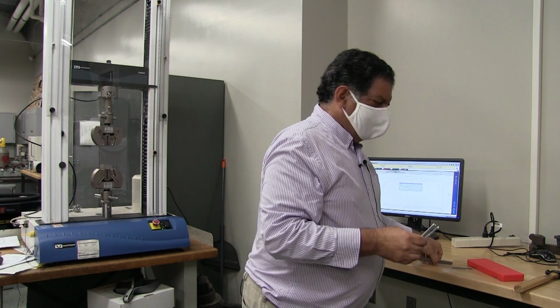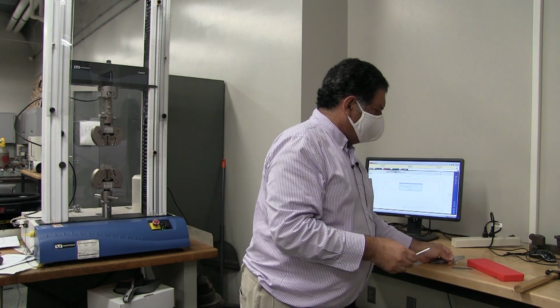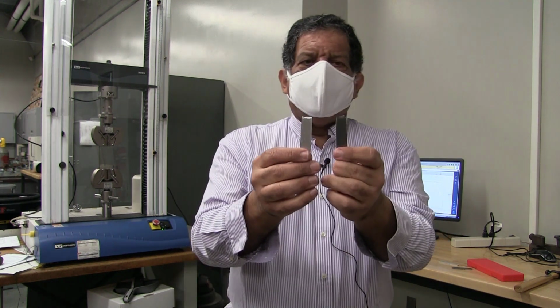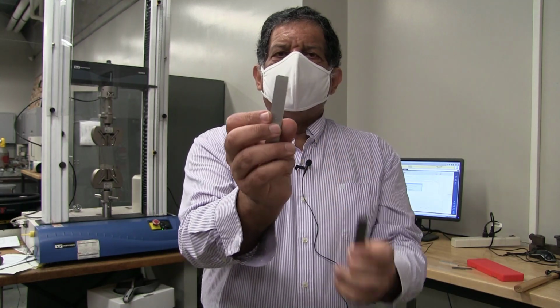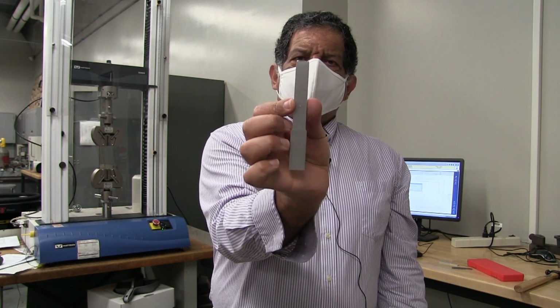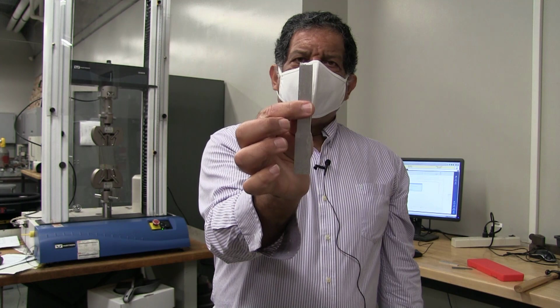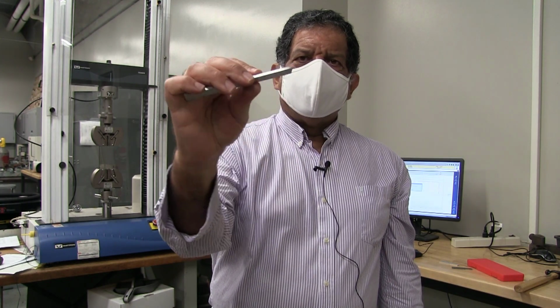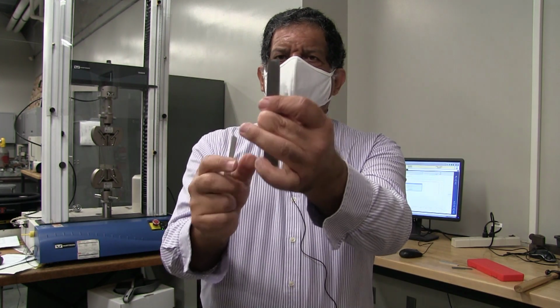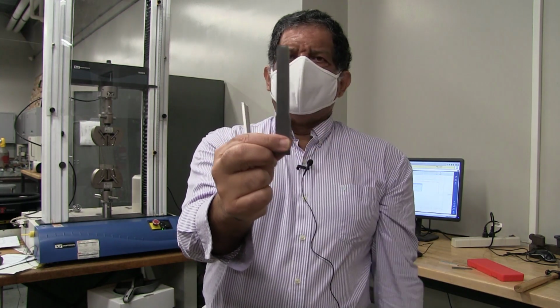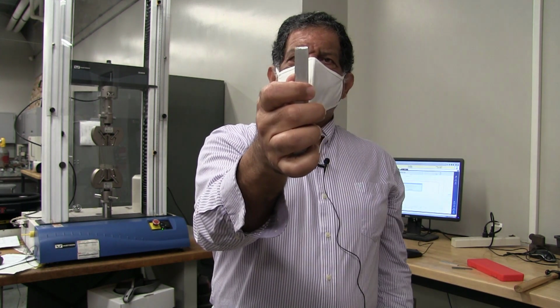And there you have it. And you can see actually the fracture is quite different between the steel and the aluminum. The aluminum, if you notice, the percent reduction in the area is fairly small. It's just a clean shear fracture. The steel necked a lot. The aluminum didn't neck very much.